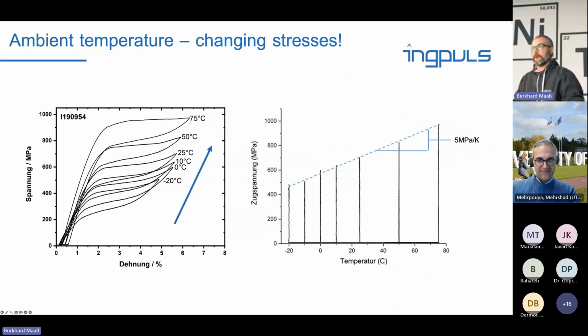And you see here, these were tensile tests, just quick and dirty with the same specimen, just changing the temperatures in the climate chamber from -20 to +75, so almost 100 Kelvin of difference. And you see that our upper plateau stress goes from 400 megapascal to almost 1,000 megapascal. That means if you build a machine frame where you want to put in your material as an elastocaloric cooling material, you would need to build it so strong that it can withstand these almost 1,000 megapascal.